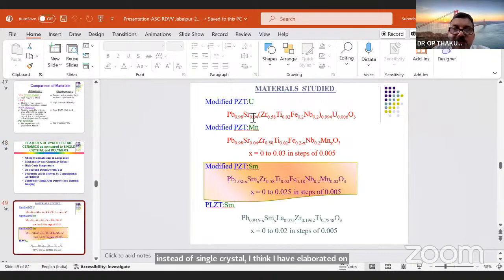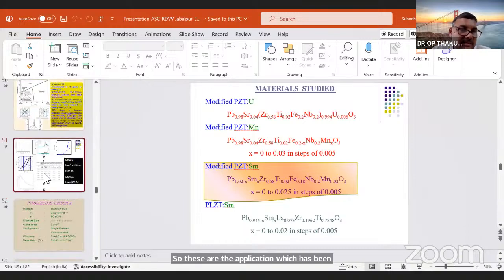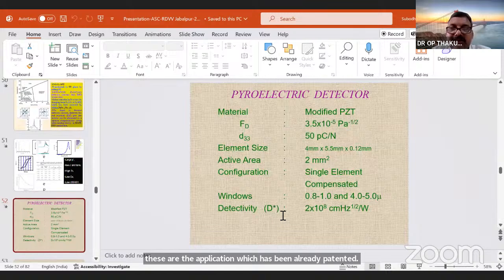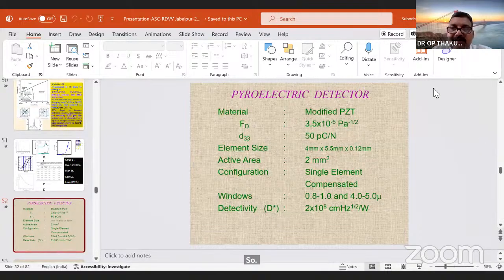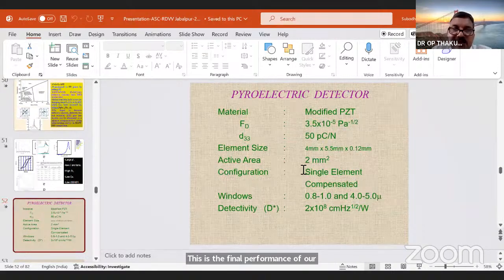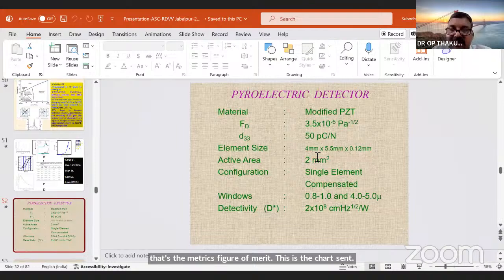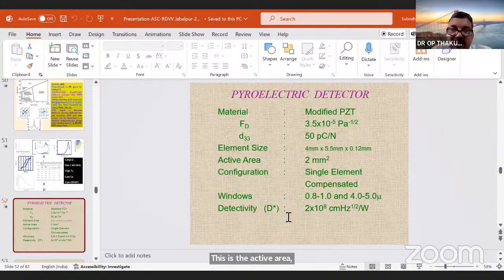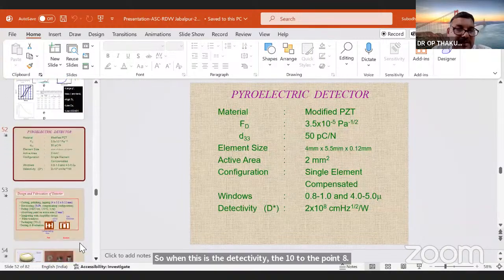So this is the final composition that we have taken for our current problem. These are the applications which have already been patented. This is the final performance of our detector. This is the materials figure of merit. This is the charge coefficient. This is the active area. This is the element size, 4 mm by 5.5 mm, with 120 micron thickness. And this is the detectivity, 2 into 10 to the power 8. That is the detectivity. It is good.